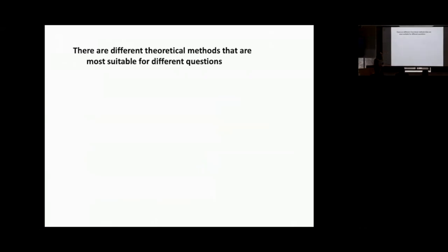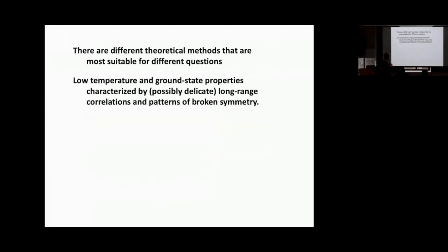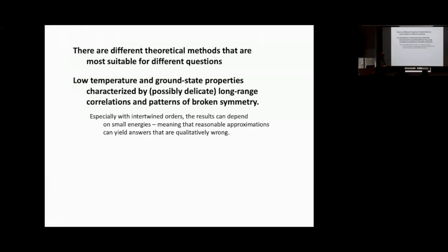Okay, so there are different theoretical methods that are suitable for different sorts of questions. The low temperature ground state properties, especially in the presence of intertwined orders, have possibly very delicate interplay of long-range correlations, which determine the ultimate pattern of broken symmetry. And so this means that even very reasonable and generally reliable approximations can yield answers that are just wrong, in the sense that if they get the balance between two very nearly competing phases wrong, you can give a right description of a wrong phase.